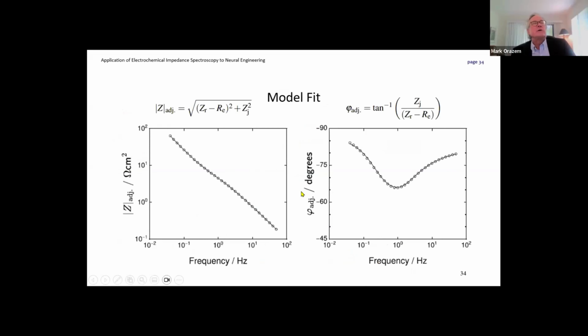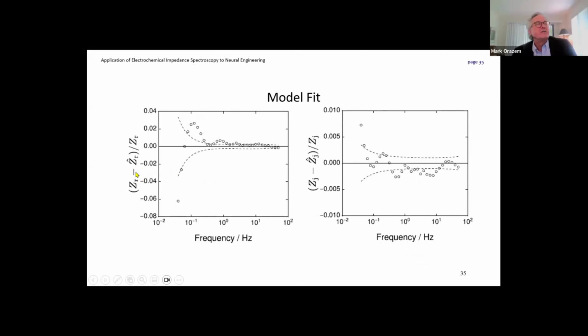The model fit the data really well. To be honest, if I plot the modulus versus frequency, it always looks good. It doesn't matter how bad your model is. Phase angle is a little bit more sensitive. So that's saying that it looks really nice in the phase angle. If we look at the normalized residual errors, and compare that to the noise level of the measurement, we're seeing that there are some differences. But in fact, these numbers are really quite good.